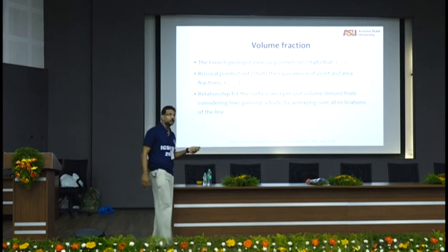Volume fraction. So the French geologist Delesse said in 1848. So again, don't think that somebody created this last year. Okay, it's been there for 170 years. We do this enough number of times, my area fraction of voids will be equal to the volume fraction of voids, which means you can realistically upscale from 2D to 3D if you have enough number of images. Basically, your software helps that also now. You tell the software to calculate all these images instead of doing one. And then you go for lunch. By the time you come back, it would have done the calculations. Which means from 2D to 3D, it becomes a very useful tool.